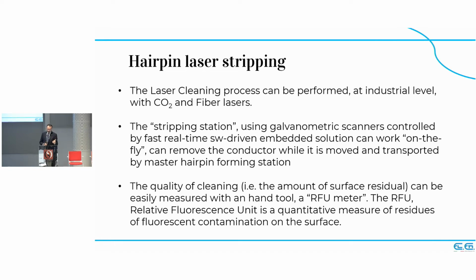The quality of the cleaning, meaning how much of the isolating coating of the copper is removed, at the very beginning looked to be an easy job, because the copper looked very clean after just a quick pass of CO2. But then we realized that the micron-thick residual that was on the copper was not really friendly with further processes like welding. What we base our feedback in the cleaning, the stripping, on is the RFU meter, a relative fluorescence unit meter that considers how much fluorescent contamination has been left on the surface.